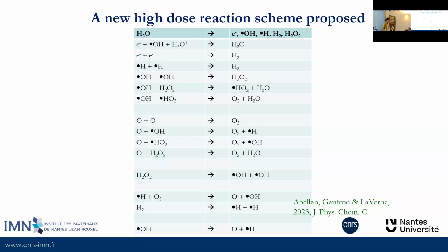So dynamics in water will disrupt the hydrogen bond network, but you really need that extra level. I don't actually know enough about Raman to say how they account for that, but I would predict the difference between the sub-millielectron volt energy resolution that you get with Raman spectroscopy and the 4 to 5 to 6 millielectron volt energy resolution that we get with EELS is the ability to distinguish between normal OH stretching in the H bond network and these types of radicals.